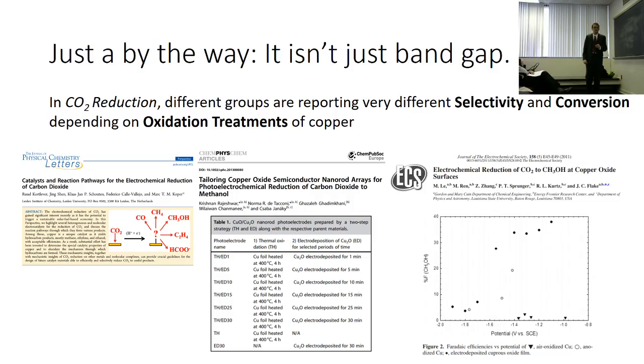By the way, it's not just band gap that's one of these inconsistent properties for copper oxide. If you look at the catalysis literature for CO2 reduction, copper and copper oxide are used a lot, and they're getting lots of different selectivities, conversions, and products depending on the treatment of their copper oxide — how they make it. But there's a lack of characterization about what in their treatment is changing the material. At least they acknowledge this is a problem — they know they're getting different things.